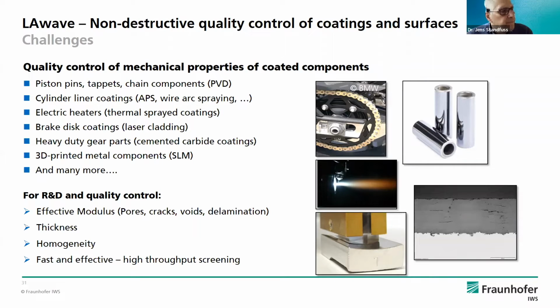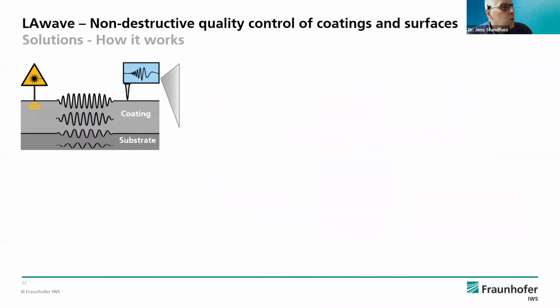What you want to control is the quality of the cladding layer with respect to pores, cracks, and also delaminations, and to characterize the thickness and the homogeneity, and this should be fast and effective with a high throughput. One principle is the development of the so-called LAwave, non-destructive quality control for coatings and surfaces.